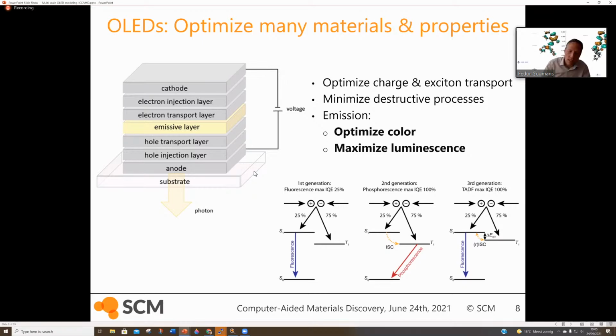So we would have our exciton giving rise to 25% singlet excited state, which could fluoresce directly, and 75% triplet state, which would be close in energy to the singlet state. And if there's enough energy, it could interconvert to the singlet state and then fluoresce. So since that is thermally activated and it's delayed fluorescence, that type of emission is called thermally activated delayed fluorescence, TADF. Okay, so let's say you want to make an OLED device.